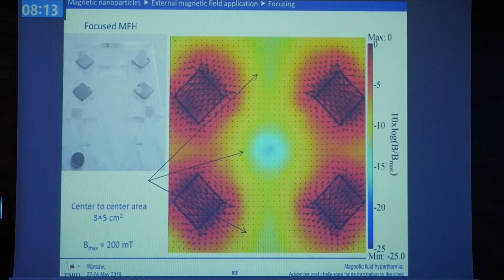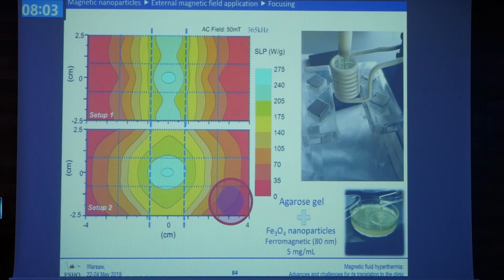And you can see here already with 4 permanent magnets, we have a field-free area in the middle. When we measure the SLP in this area, it is the highest. But when we measure it everywhere else, where the nanoparticles are fixed because of the external static field, the SLP is very low. These are the red areas as you see here. Okay? We have tried that with nanoparticles inside agarose gel, and it worked very nicely. We're trying to publish that now.